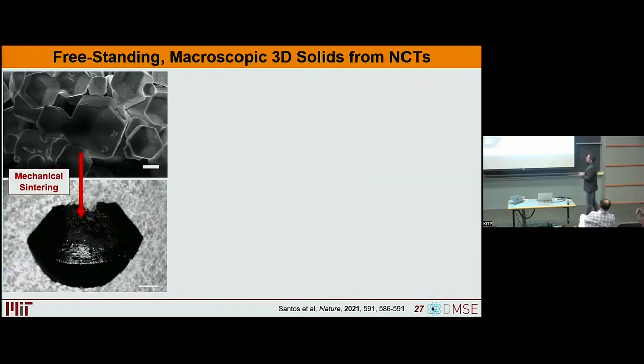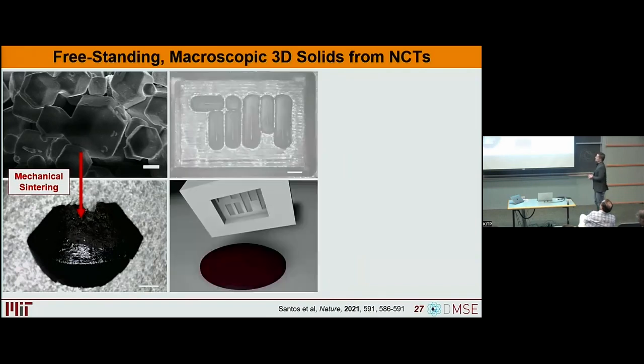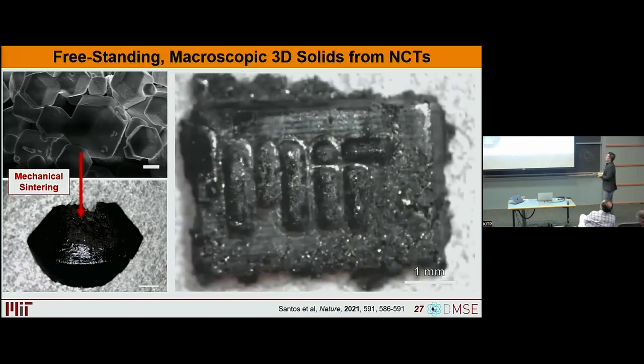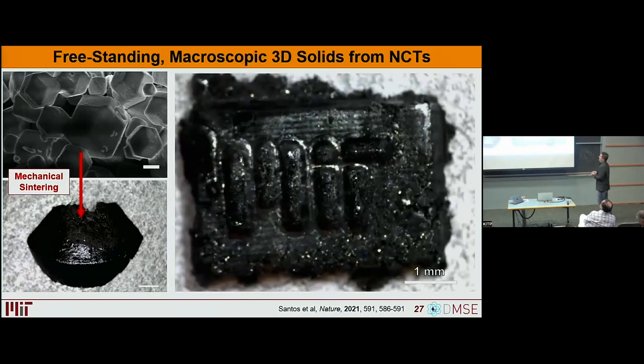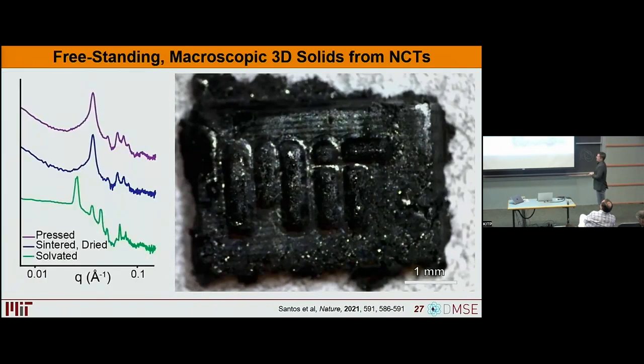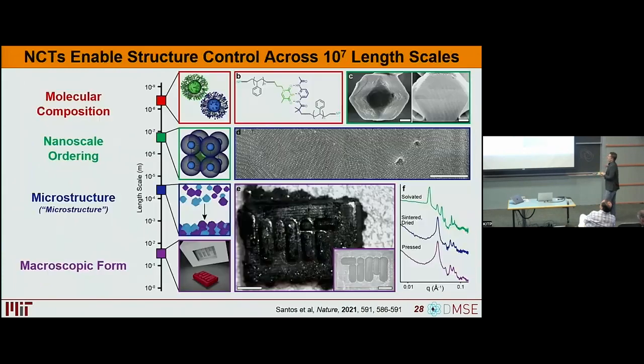We can make a bulk material that we can pick up and hold in our hand, but if we press it into a mold with some sort of recognizable shape and we apply just a little bit of pressure, we can actually make a material that now has a macroscopic shape to it. But if we crack it open or if we look at it with X-ray scattering, we can see that ordering is maintained even through all of this processing. So what we have now is a method of controlling material structure across 10 to the 7th length scales simultaneously, all the way from the composition through the nanoscale organization to the microstructure and up to macroscopic form.